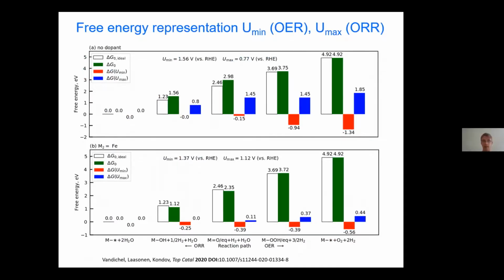So here we can represent things differently. What we have calculated here are the free energy as a function of the different states calculated. So we calculate the Gibbs energy levels. That's the same as the step plot. But now we can visualize this delta G as a function of U-min for the OER process and as a function of U-max for the ORR process. And we have to read this graph from left to right for the OER process.